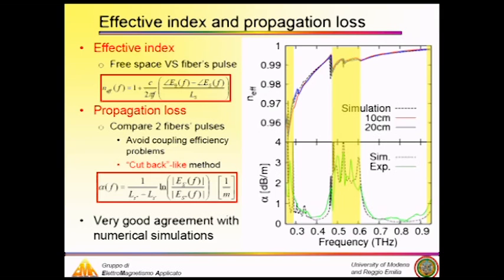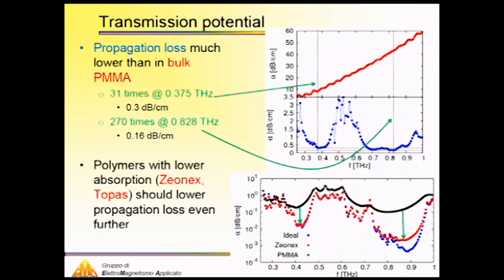Here you can see a comparison between the numerical result represented with a dashed black line and the experimental one. And as you can see, there's a very good agreement for both the dispersion and the propagation loss. But talking about raw performances, here we can compare the propagation loss shown before with the bulk PMMA absorption reported with a red line. And as you can see, for both the first and the second transmission window, we have a strong improvement with respect to the bulk material, giving us a propagation loss as low as 0.3 and 0.16 dB per centimeter.